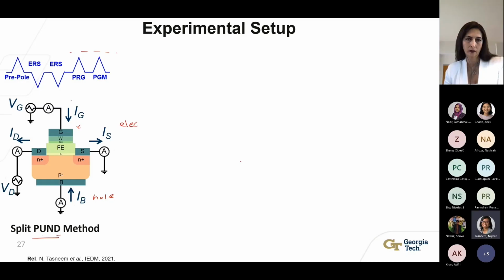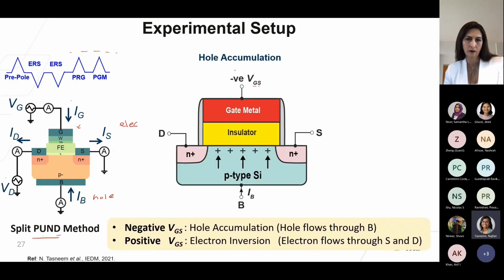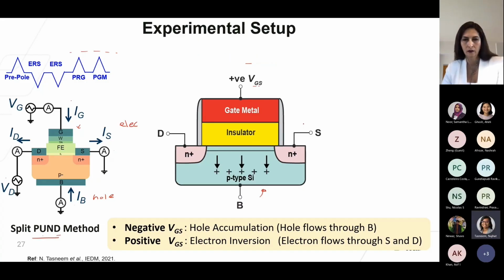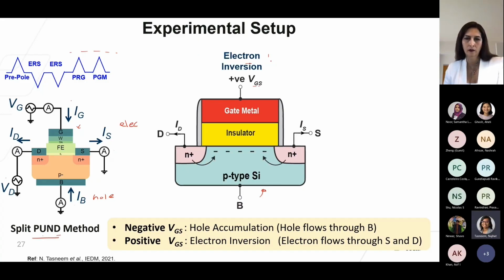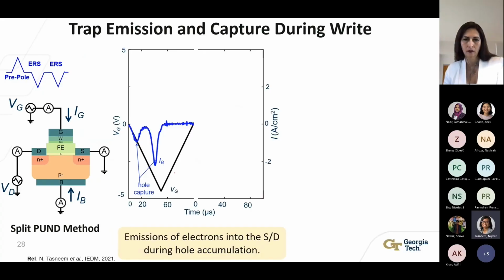Now, in case of an N-type device, when we apply a negative gate voltage, the device should go into hole accumulation, and there should be hole currents flowing through the body terminal. And then when we apply a positive gate voltage, the device eventually goes into electron inversion. And in this case, we should see electrons flowing through the source and drain. Now, keeping this in mind, let's look at the experimental results of this split PUND technique. So first, we applied a negative erase pulse on the N-type FeFET. And as expected, the device goes into hole accumulation, and we should see hole current flowing through the body terminal, shown by this blue curve over here.